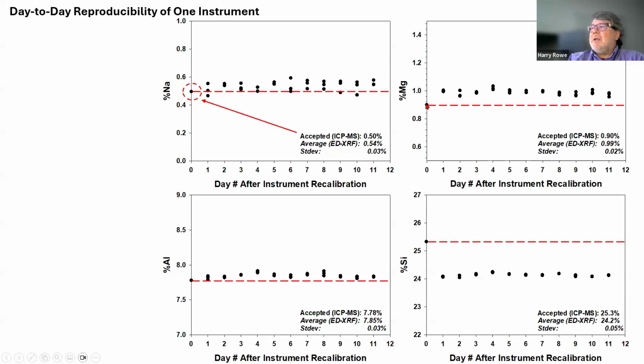For magnesium, this is the right answer. And this is the answer I get for this one pellet, one of the 41. You're always going to be off a little bit because you're just looking at one pellet. I just decided to pick one. And this is the precision. And you just judge the accuracy here by looking at the accepted versus that average value there. Silicon, we're a little bit low on this one. We always have been. There's nothing that I can do to correct it to get it back up to that line. But it is very consistent. And of course, there's another pellet that's a little bit on the other side of the line, of that 41 pellet calibration line.